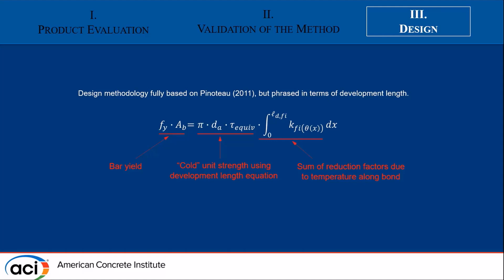And then the integral part here that you see is saying, how do we modify the development length along the bond stress along the length, or how do we take the individual contributions of the fire, of the capacity of the adhesive under fire conditions over the length. This can be expressed as an integral or as a summation. And this is showing that the tau equivalent in this equation is based on the cold development length.